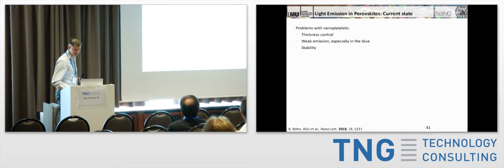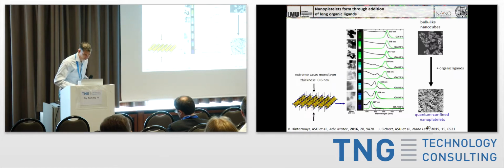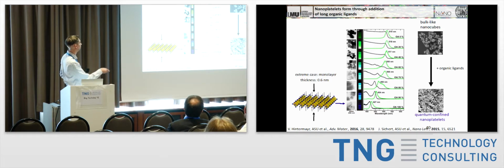The problem with the nanoplatelets that we had in this case is thickness control. So if you look at the spectra in there, you can see that they're not nice, ideal single emission spectra, but they're actually quite large and bulky. And that's due to the fact that we don't only have a single thickness in here, but we have different thicknesses, and each of these have a slightly different absorption and emission spectrum.